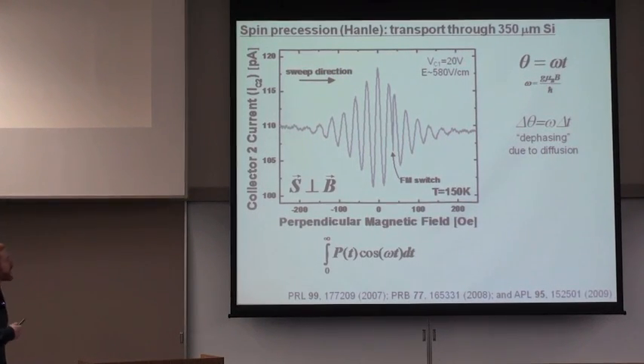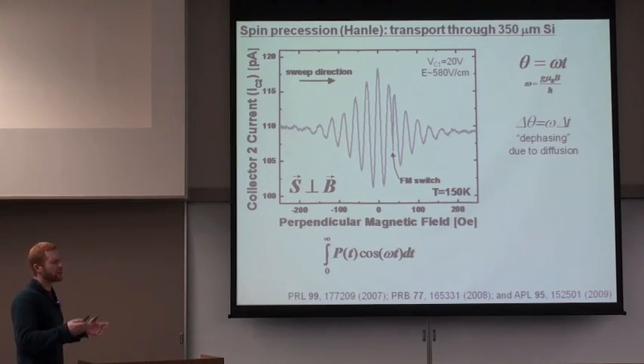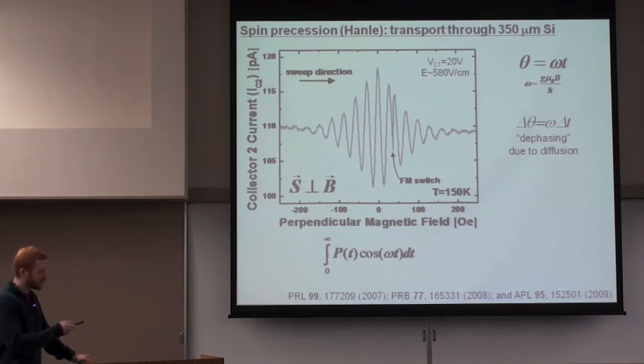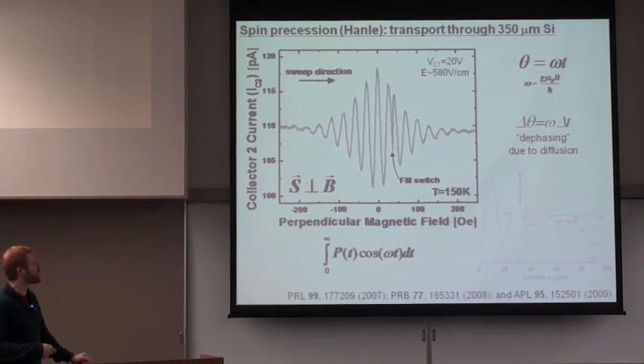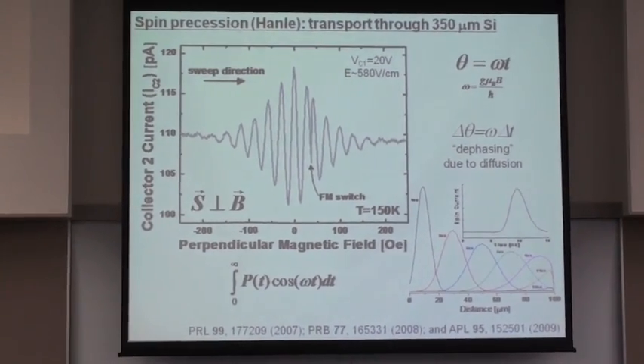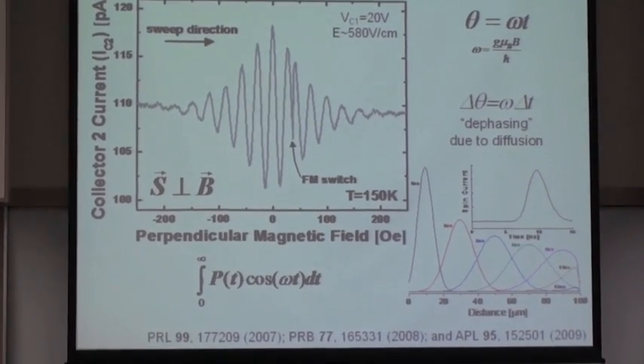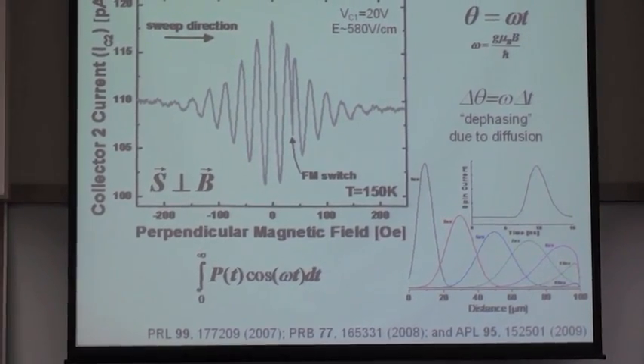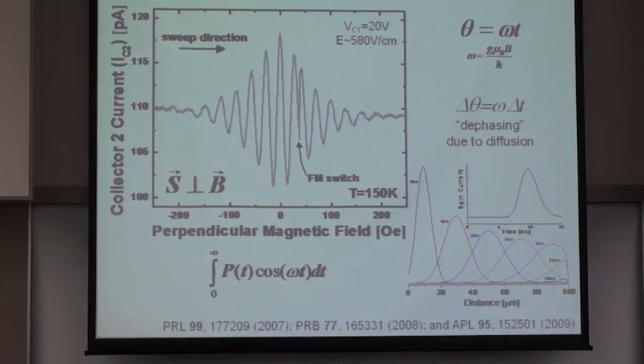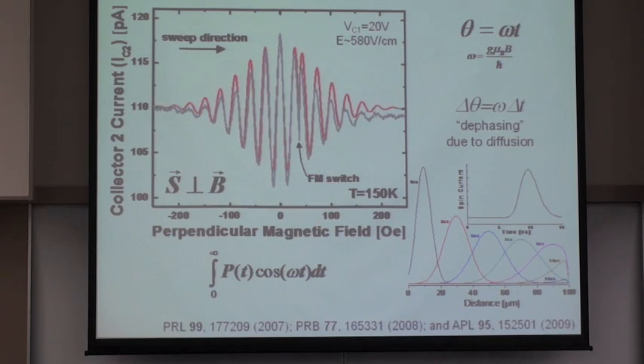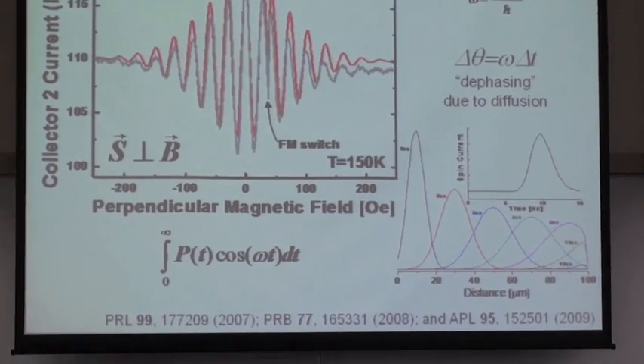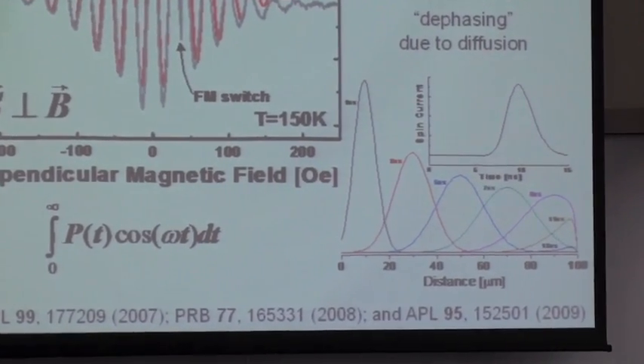Now, of course, we can account for this simply by adding up all of these cosine contributions from electrons with a definite transit time by weighting with the transit time distribution for our spin current. And the transit time distribution for the spin current can be very simply modeled with the drift diffusion equation Green's function, or impulse response. And this model has several tunable parameters, the spin drift velocity and the spin diffusion coefficient. And we can change those parameters to fit our data. So that's the red curve here, and you can get pretty good correlation.